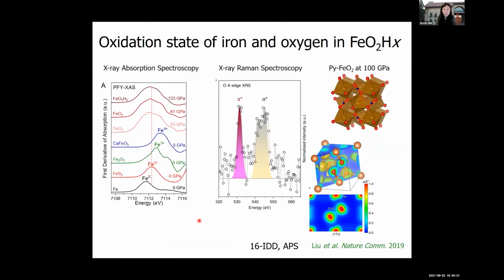Okay, so we measured diffraction. We also wanted to look at the oxidation state of iron and oxygen in this compound. So Jin collected a number of X-ray absorption spectra on the FeO2H and also the hydrogen-free version, just FeO2, and a number of iron standards. And here's a plot of the first derivative of the absorption edge. The peak for this FeO2 compound lines up very well with Fe2+ compared to more reduced Fe0 or more oxidized Fe3+, Fe4+. And if this iron is closer to ferrous iron, then it also suggests for our charge balance that the oxygen has to be more oxidized, so closer to -1 than the normal -2 in oxides.